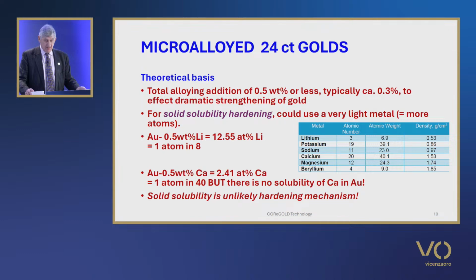If we assume a maximum alloying level of 0.5% and take the lightest metal in the table, lithium, then a gold 0.5% lithium alloy, for example, is 12.55 atomic percent lithium, which is within the solid solubility range. This is 1 atom of lithium to every 8 atoms of gold.